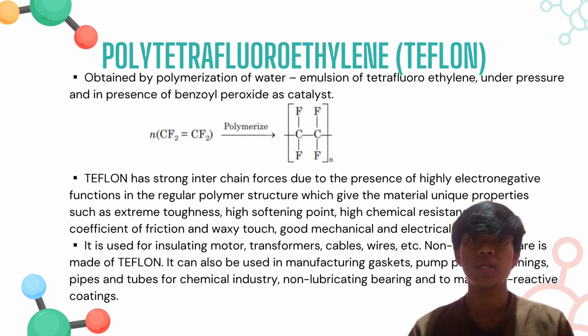Next is polytetrafluoroethylene or Teflon. It is obtained by polymerization of water or emulsion of tetrafluoroethylene under pressure and in presence of benzoyl peroxide as catalyst.